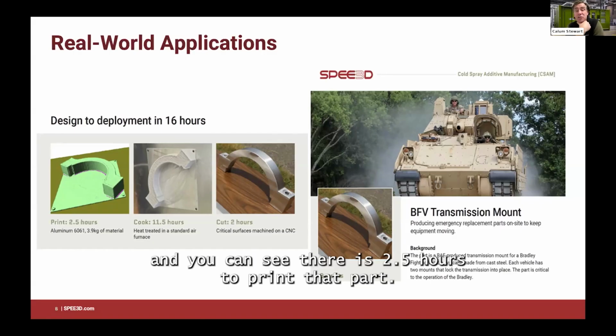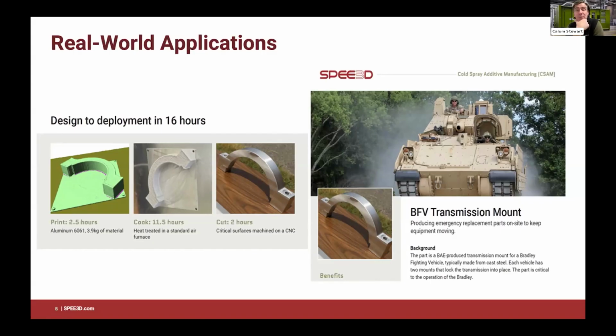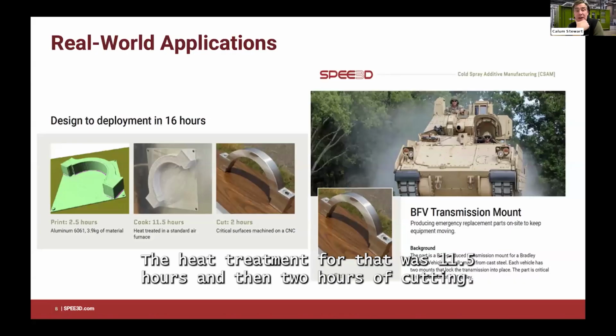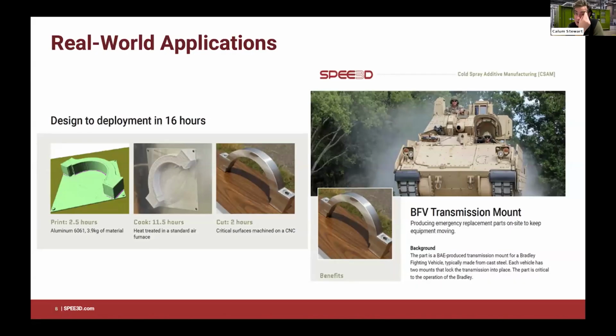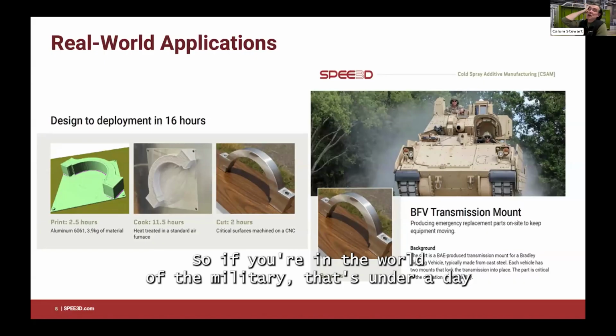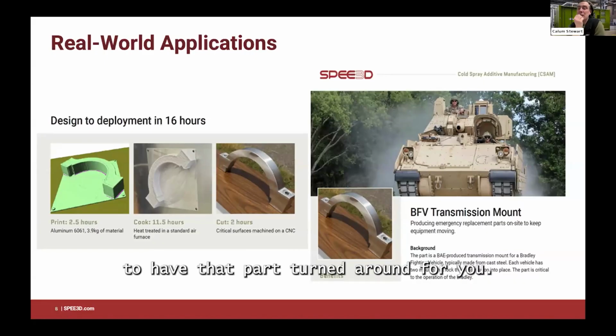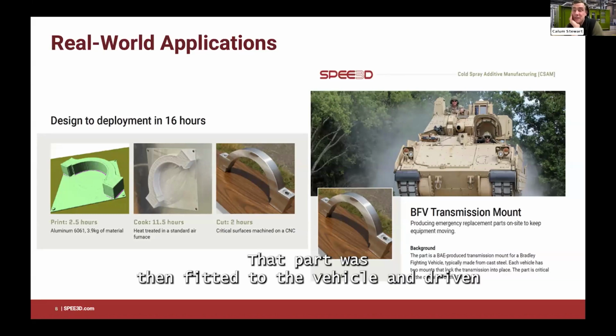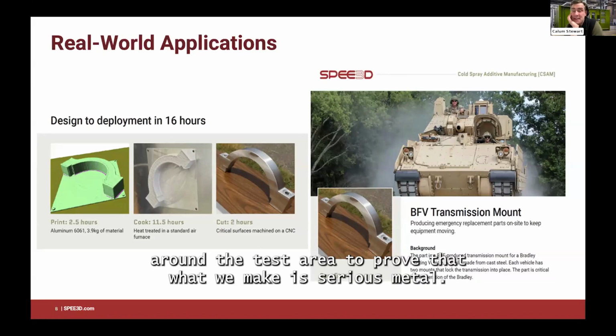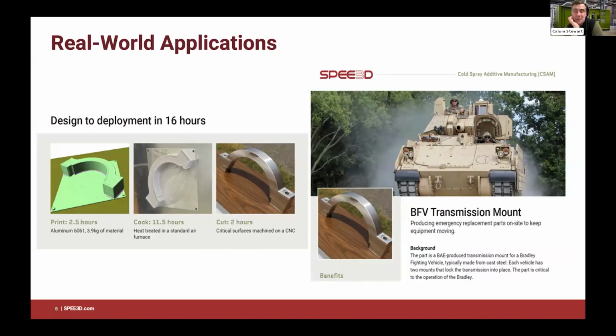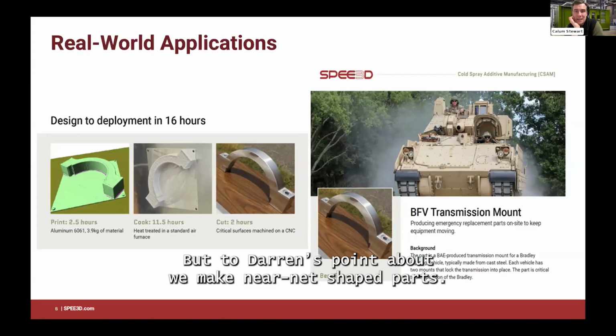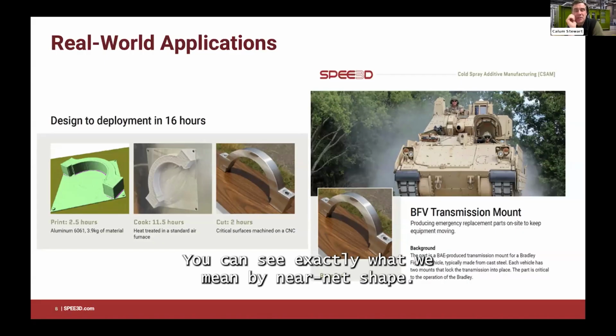And you can see there it's 2.5 hours to print that part. The heat treatment for that was 11.5 hours, and then 2 hours of cutting. So if you're in the world of the military, that's under a day to have that part turned around for you. That part was then fitted to the vehicle and driven around the test area to prove that what we make is serious metal. But to Darren's point about we make near net shape parts, you can see exactly what we mean by near net shape.